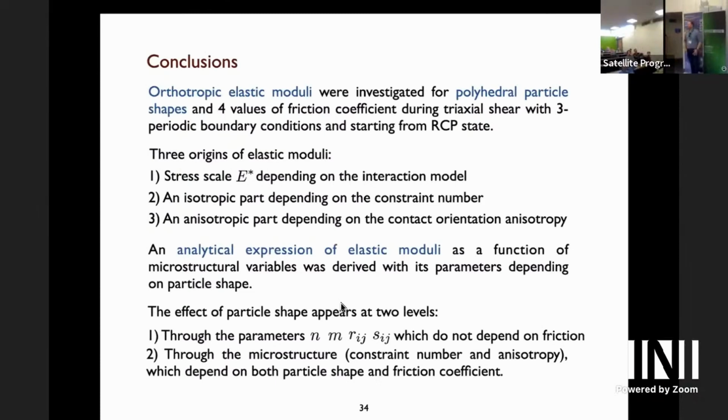Well, anyway, we can't use Hertz because we don't have well-defined curvatures in the model we have, because these are spheropolyhedral. So we can use the expressions of local elastic laws between 2 cylinders, for example. There are contact theories for wedge on face. Yes, the contact stiffness changes with compression. That can be done. That can be an improvement.